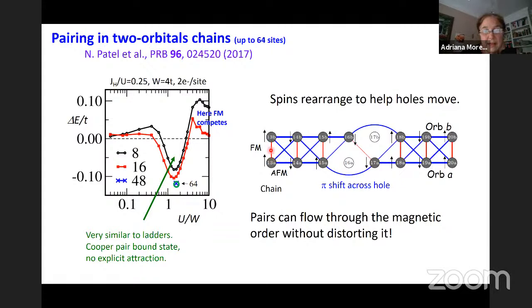The red lines indicate spins that are ferromagnetically aligned, and the blue lines indicate spins that are antiferromagnetically aligned. These are ferromagnetically aligned because of the Hund coupling, and this is the antiferromagnetic order that results because of U. What we notice is that the holes are in different sides of the chain because of the Coulomb repulsion.